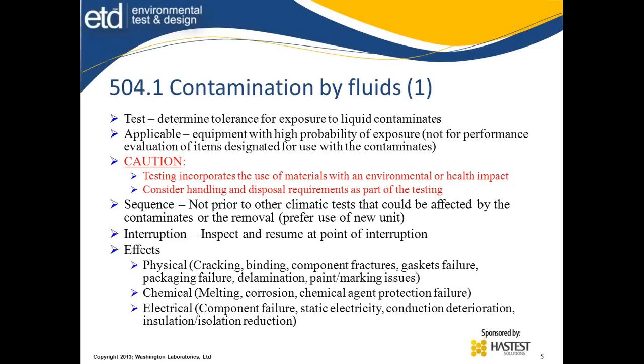A lot of folks think that contamination by fluids is an external event, that they look at the surface layer and say, well, okay, all the connectors stood up to it. But what's going on in that hermetically sealed connector? Did it stay long enough there to creep in through the connector? Did it have an effect inside, and it's taking some time to examine? So opening the cover and saying, I didn't see anything pour out, doesn't necessarily mean that I'm not getting swelling or it's being absorbed by the materials and we don't get the good visual indicator. So detailed inspection is a necessity. You have to pay attention to the output of this thing at the end of the day.